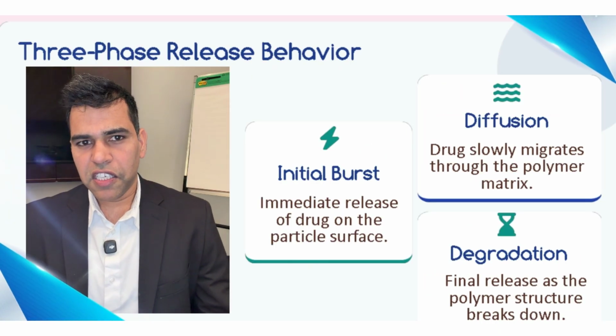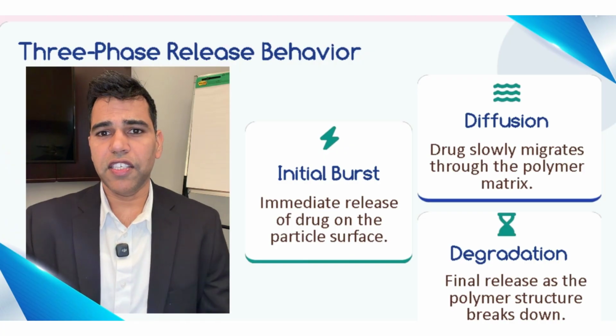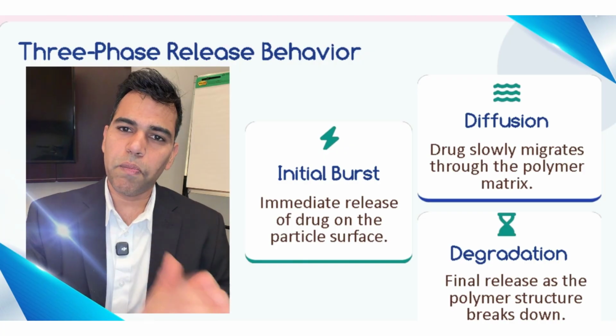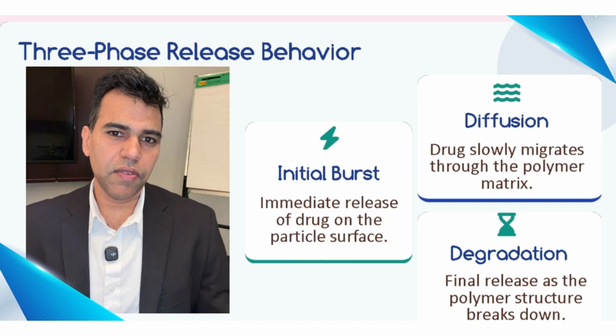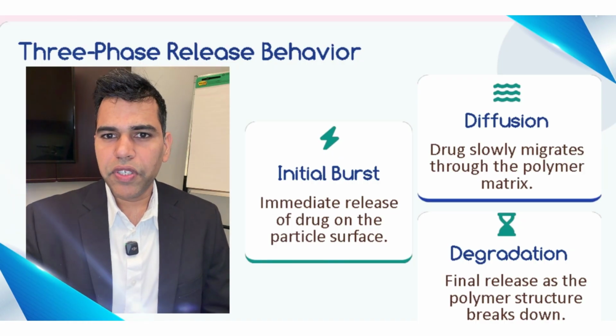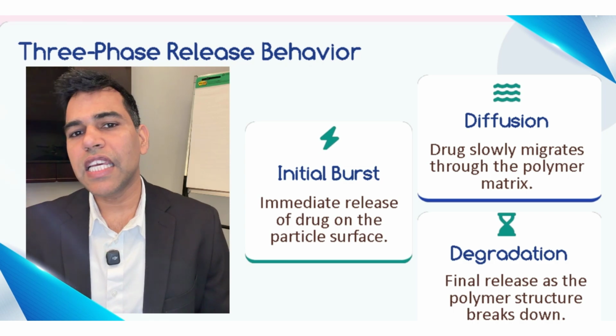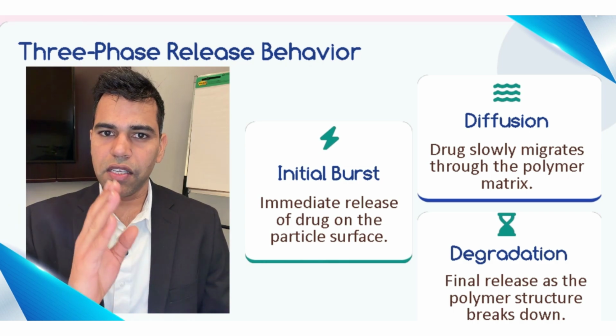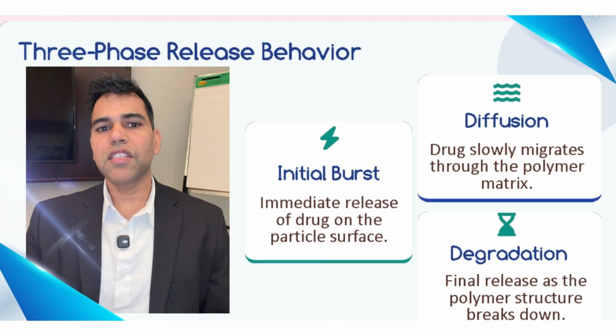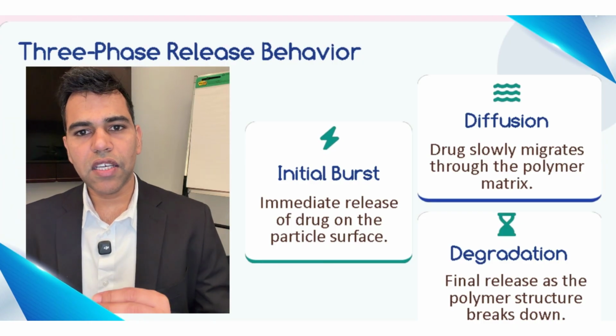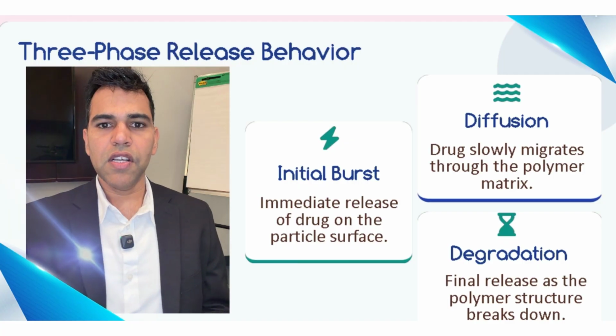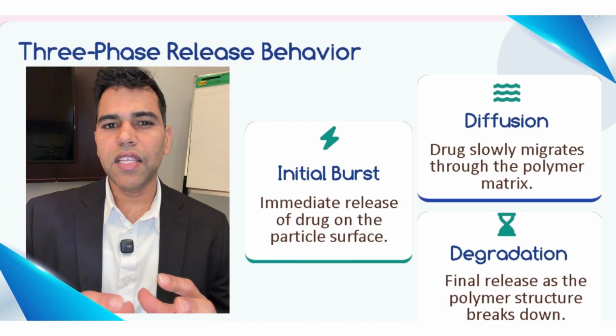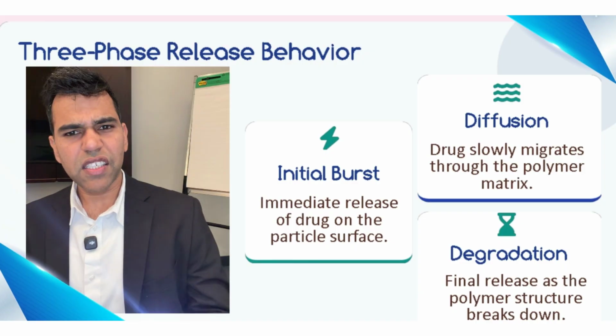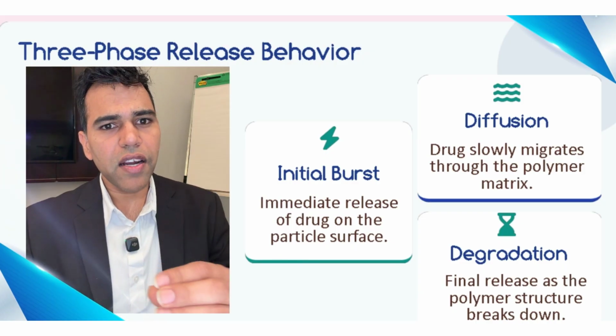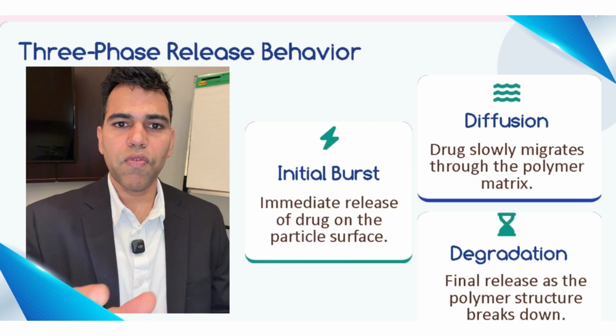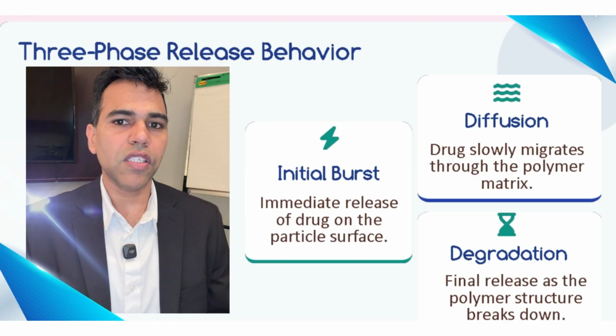The 3-phase release problem. Now let's talk about the drug release, because this is where the complexity becomes almost philosophical. Lupron Depot doesn't release leuprolide in a single clean wave. It follows a characteristic triphasic pattern. First, there is an initial burst. Leuprolide sitting on or near the microsphere surface releases quickly in the first few days. This matters clinically. It's partly responsible for the initial testosterone flare that clinicians warn patients about.